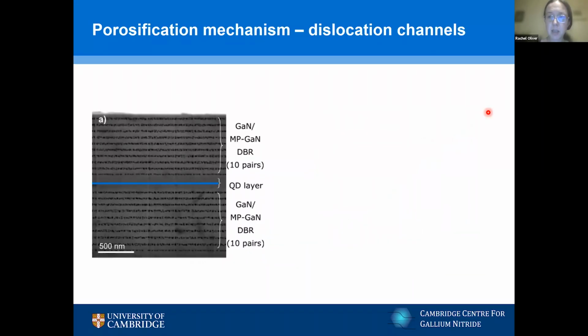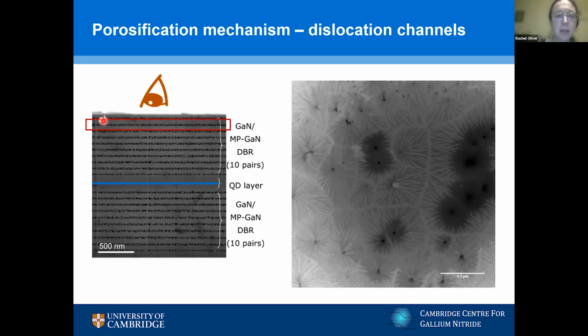I'm just going to unpack that porosification mechanism that I've mentioned, that we're etching through defect channels. What I've got here is a cavity structure with a porous DBR above and below a quantum dot layer in the center. But what I want to focus on is that we did a transmission electron microscopy experiment where we took out just one layer of the porous DBR. We've prepared this as a very thin foil that will be electron transparent in the transmission electron microscope. This is a scanning transmission electron microscope image, STEM. STEM is generally thought of as a technique which gives you atomic mass contrast, where heavier elements are brighter. Here we've only basically got gallium nitride, so it's really just giving us thickness contrast. Where there's more material, we're seeing brighter. Where there's less material, we're seeing darker.